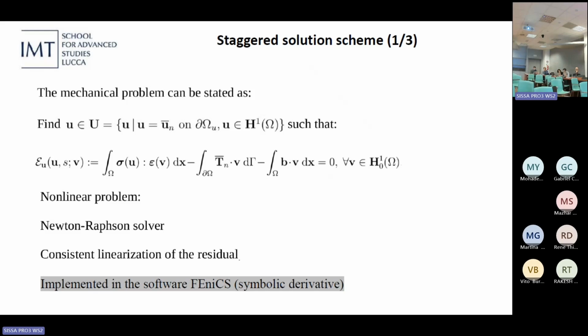Okay, so what about the solution scheme? We adopted a staggered solution scheme. Why a staggered solution scheme? Because it is known that the monolithic approach has a functional which is not convex in general, while the convexity is obtained considering two sub-functionals, one for just the mechanical problem in which the phase field damage variable is frozen, and then we solve the problem for the phase field variable, which is of Poisson type of equation, so it is known to be convex.